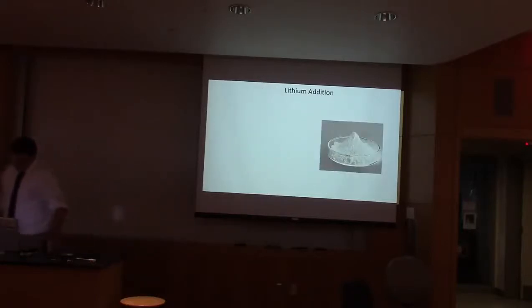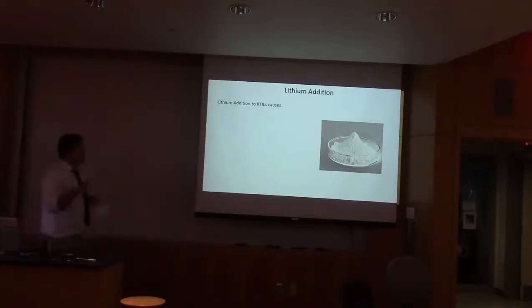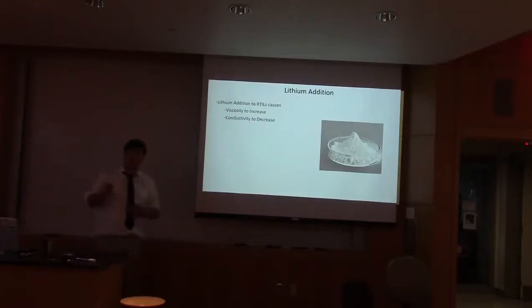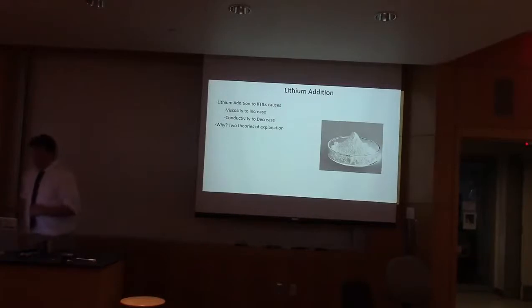Lithium addition. Specifically, we're taking lithium salts and basically just pouring them into room temperature ionic liquids. We know from previous studies on room temperature ionic liquids with lithium salt addition that the viscosity increases and the conductivity tends to decrease. What we're really trying to ask is why.